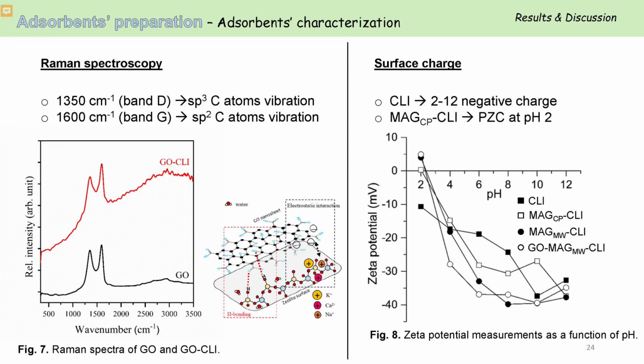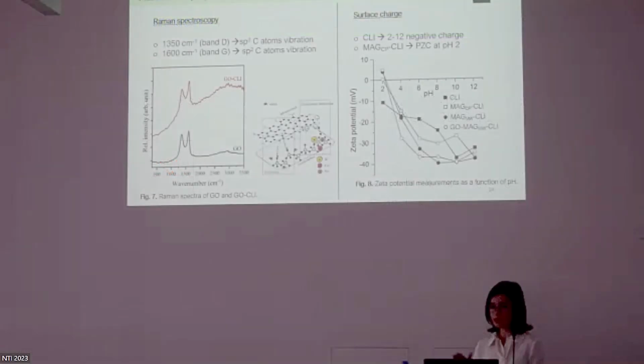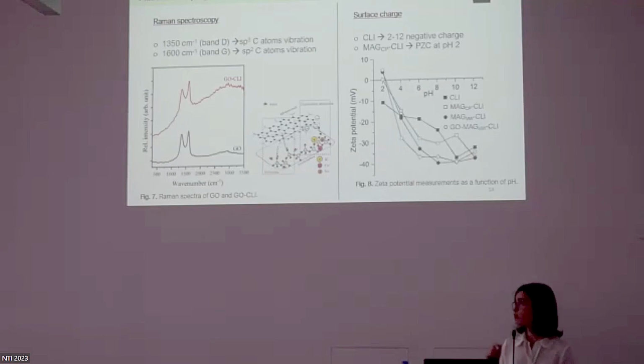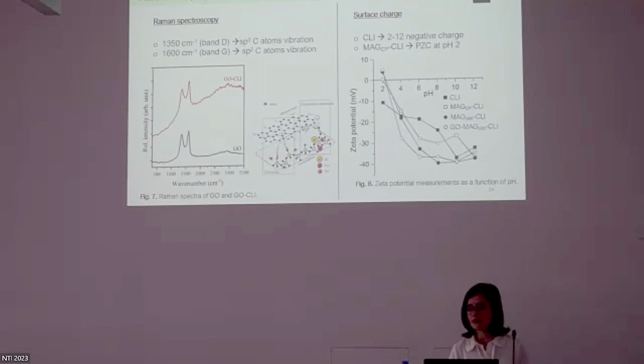Since, as I already said in the introduction, the ciprofloxacin molecule charge strongly depends on the pH, the surface charge of the adsorbents was also measured. Clinoptilolite has a negative surface charge over the entire range of pH values. The surface charge of clinoptilolite slightly changed with modifications at lower pH values, but it is still negatively charged in, let's say, a wide range of pH.